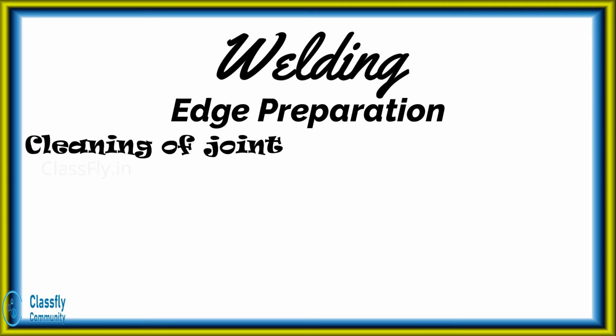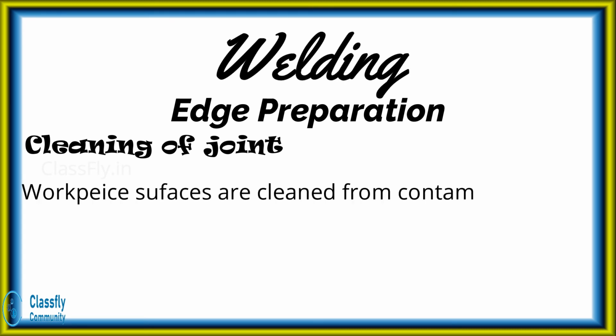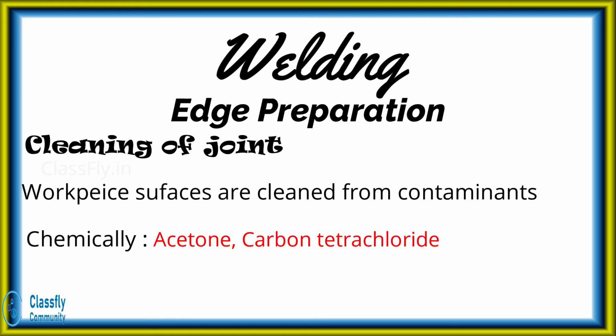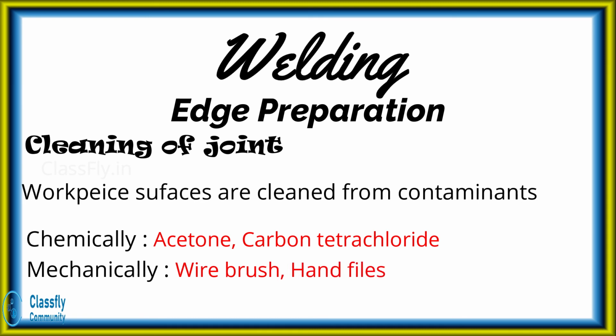Next, cleaning of the joint. Well, the workpiece surfaces are cleaned from contaminants such as dirt, grease, oxides, etc. This cleaning is done either chemically by using acetone or any other solution, or by mechanical means by using a wire brush, hand file, etc.